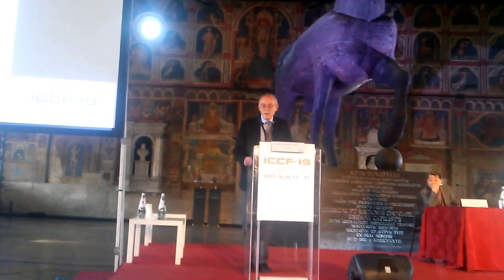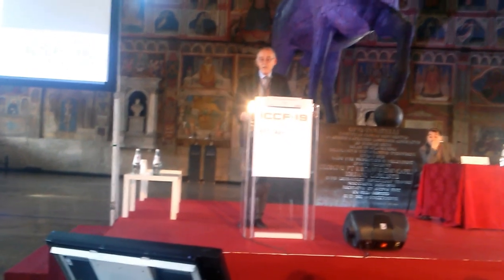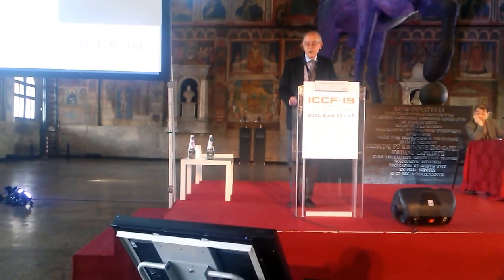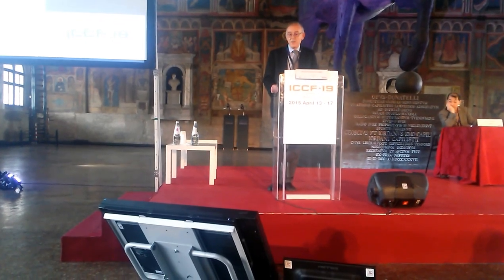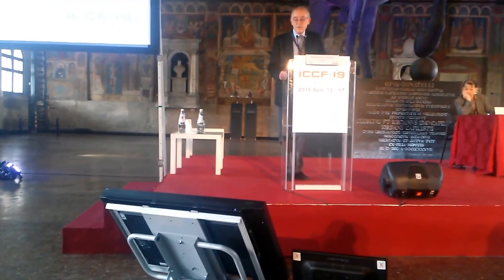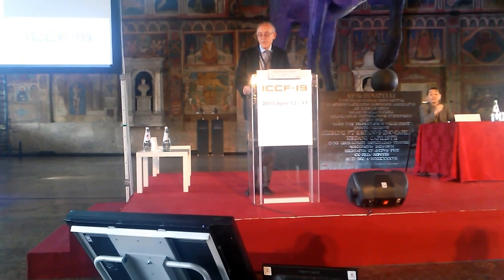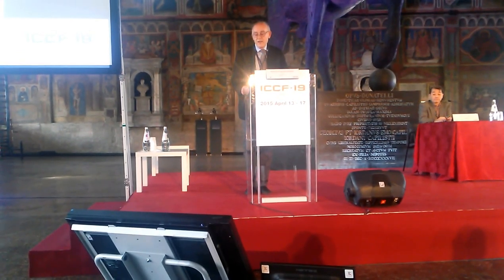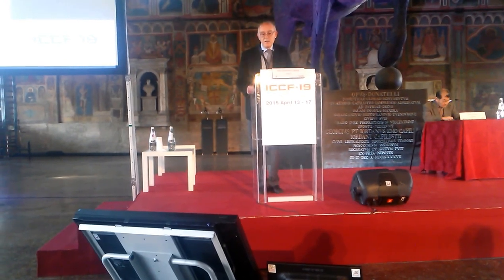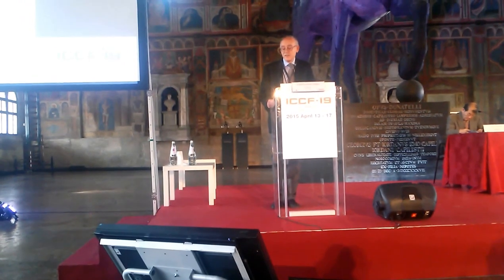This is some material coming from Luca Gamberale when he was working in Pirelli labs, and in the previous years he worked with Professor Preparata before he died. And he made experiments with heavy water electrolysis with palladium cathodes. And at the end of the experiment, he analyzed some region of the wire, finding lighter elements than palladium. C and O are usually not considered in the transmutation phenomena, because they are always present in EDX analysis. But anyway, the peak of the oxygen may in some cases be very high.